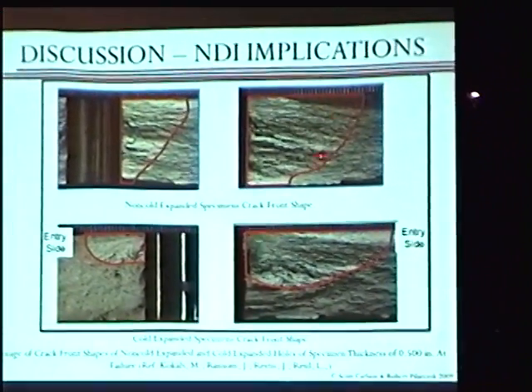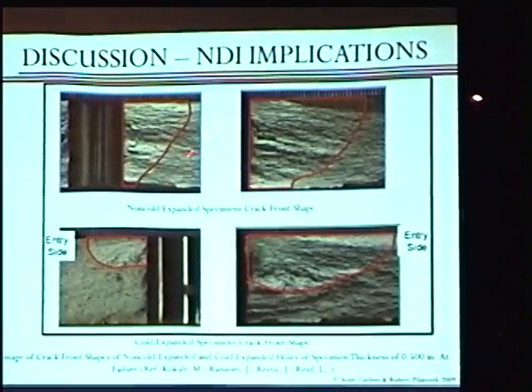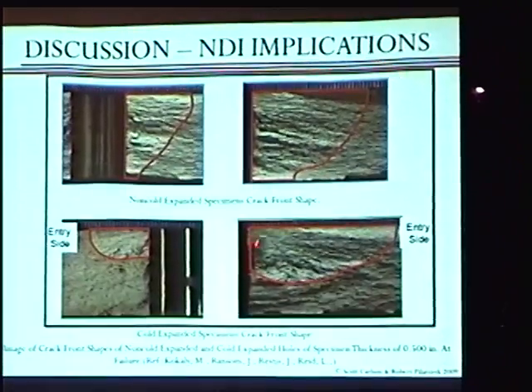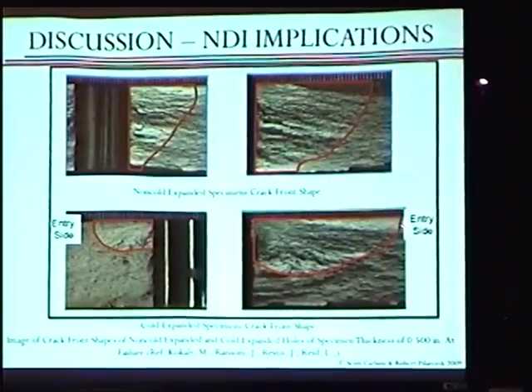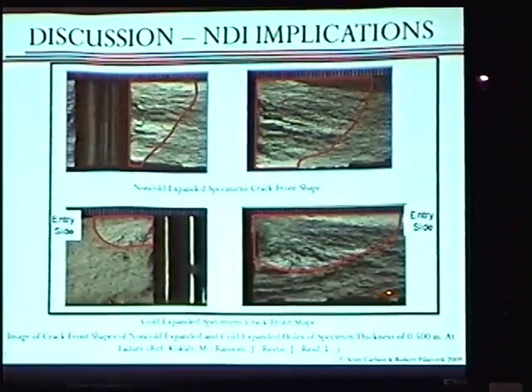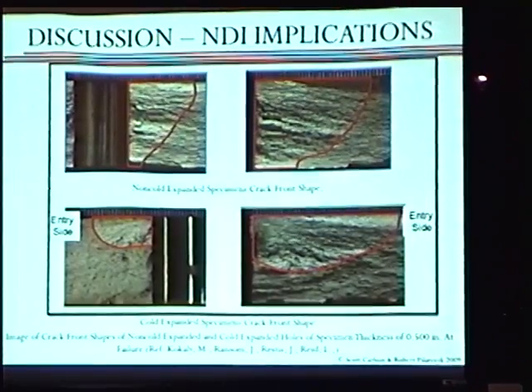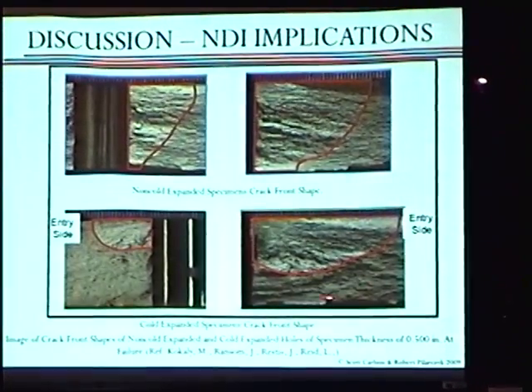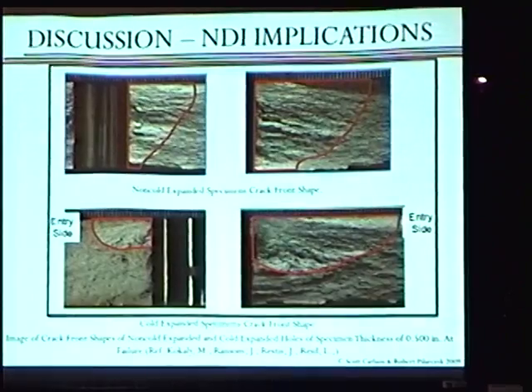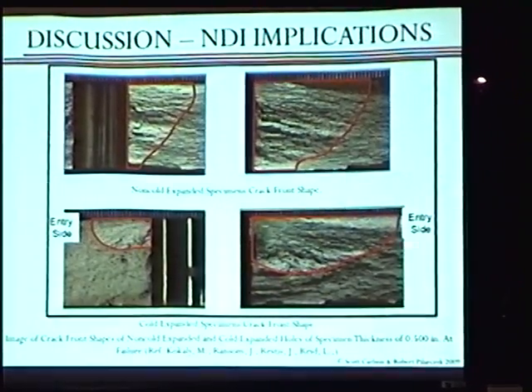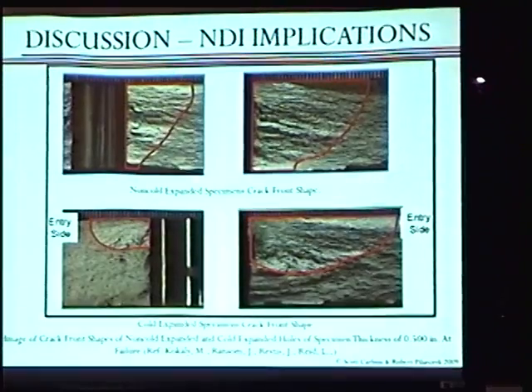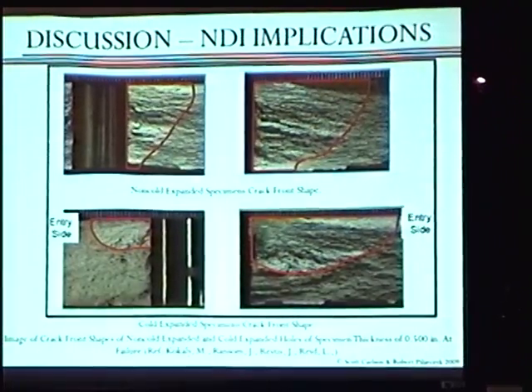This is typically what you would expect in a component that's just a standard hole. But then, think about this specimen right here. This was actually fractured. You never even saw the crack on this side and it went catastrophic. But look how long it is over here relative to thickness. Because of that high residual stress over here, the crack didn't even propagate through thickness. It just headed this direction. Path of least resistance, right?